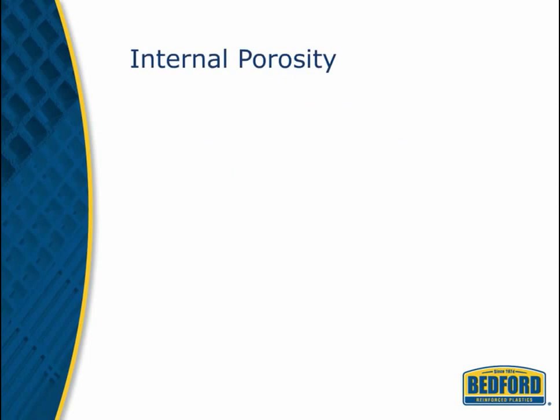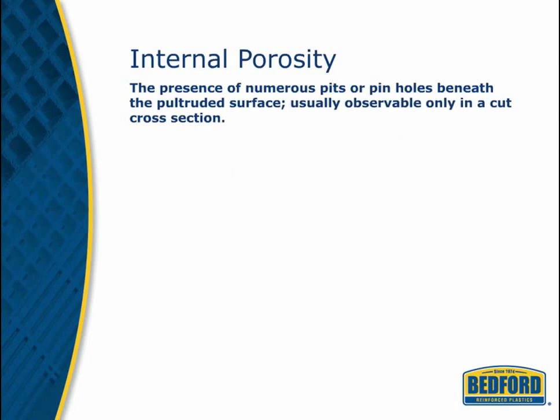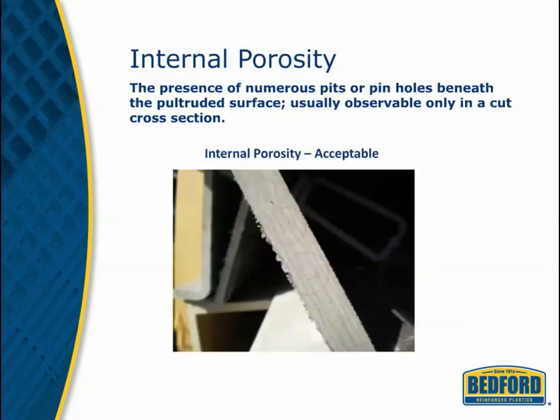Internal porosity is the presence of numerous pits or pinholes beneath the surface, usually only visible in a cut cross-section of the product. No more than two pits or pinholes are allowed for every sixteenth of an inch of thickness per one inch of width. Shapes exceeding the limit can be accepted if the properties, including water absorption, are satisfied.